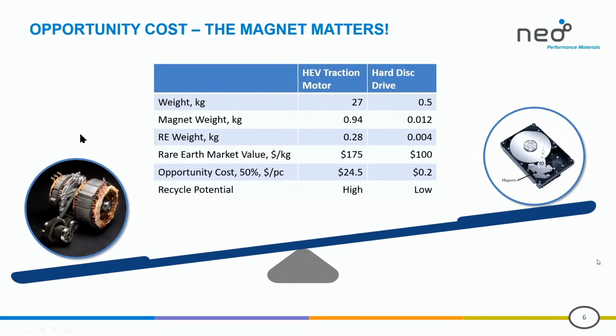So on the left here, I'm showing a traction motor. On the right, I'm showing a hard disk drive, which are two very different extremes. And when you look at this, they're very different in terms of the magnet weight. The traction motor is almost a kilo. In this case, this is for an HEV application. The magnet in the hard disk drive is about 10 grams. So it's a big difference in the total weight.